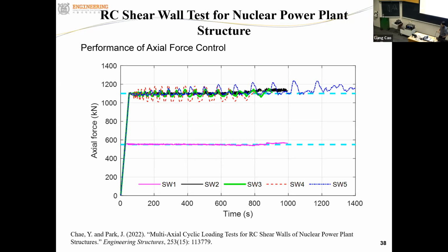Okay. That's the result of the axial force control. We conducted the unidirectional test and also bidirectional test. Unidirectional means the in-plane deformation applied only, and bidirectional, the in-plane and out-of-plane motion applied at the same time. And during this lateral deformation, the axial force is supposed to be applied constantly. So we conducted 5 different tests with different axial force. First case is the 550 kilonewton axial force, but unidirectional one. The purple line shows the controlled axial force. It's almost the same as the target force here.